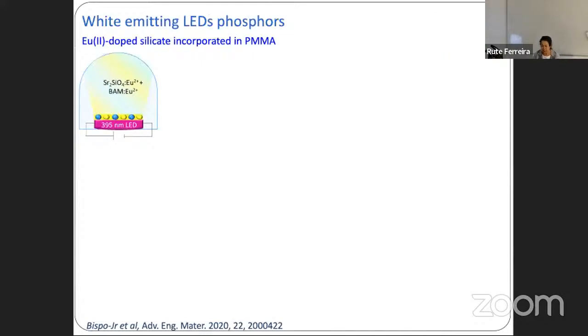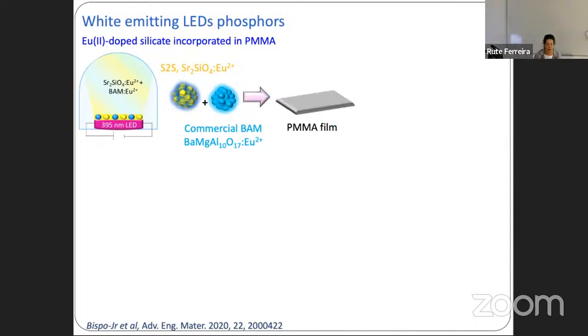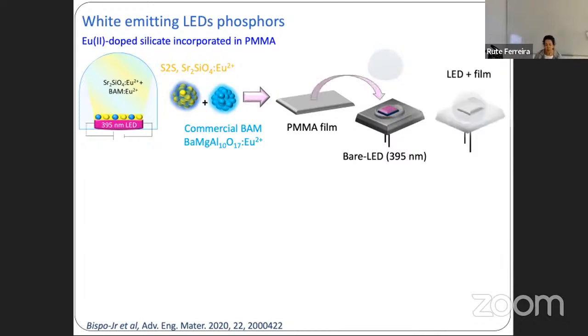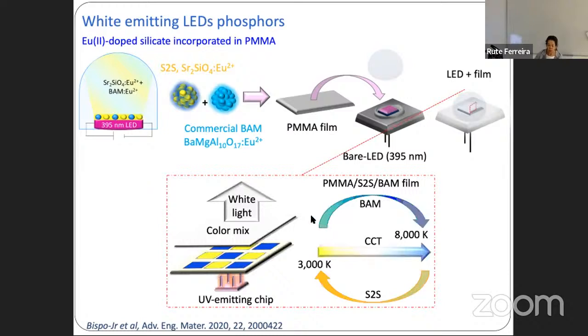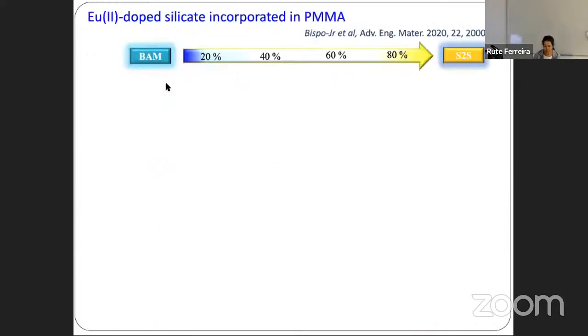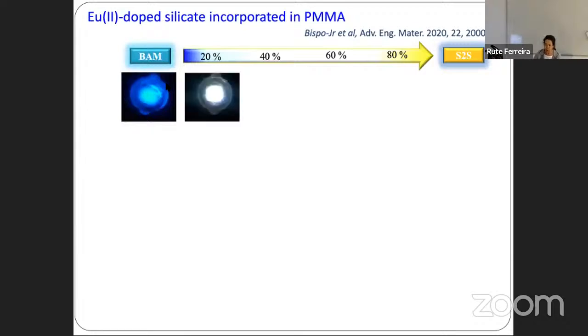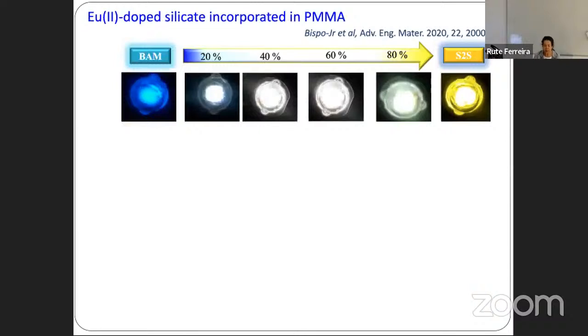The other example that I selected for today is also based on europium 2+, but incorporated into the so-called S2S silicate. And this time what we want is to generate white light with controlled CRI and CCT. So this silicate was combined with a commercial aluminum oxide in distinct ratios. Again, it was processed as a film through incorporation in polymethyl methacrylate. It was deposited on top of a bare LED, this time with a higher excitation energy, 395. And as I will show to you, we are going to use different ratios between the commercial oxide and our S2S silicate. The commercial oxide reveals a blue color, whereas the S2S silicate displays a yellow color.